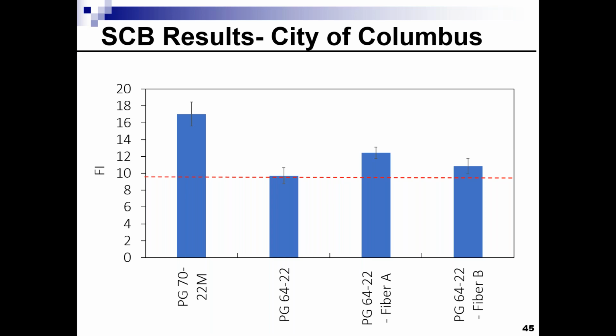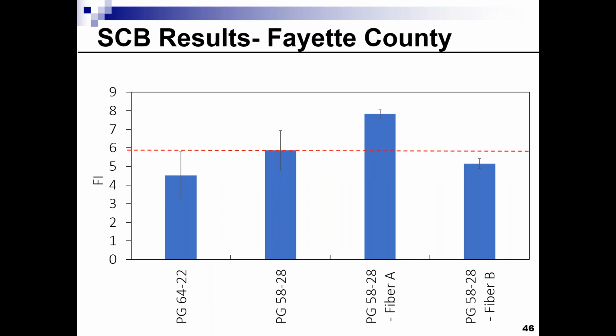The flexibility index had, in general, a similar trend. The only thing that we have seen is that the flexibility index of the polymer modified in the city of Columbus was higher as compared to the PG64 with fiber A or fiber B, as you can see here, but still both fibers had higher flexibility index as compared to the unmodified mix.